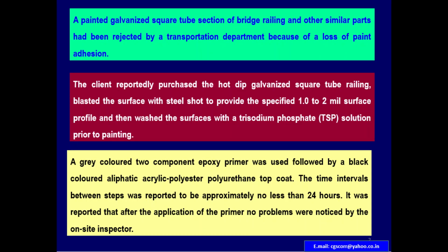A painted galvanized square tube section of bridge railing and other similar parts had been rejected by a transportation department because of a loss of paint adhesion. The client reportedly purchased the hot dip galvanized square tube railing, blasted the surface with steel shot to provide the specified 1 to 2 mil surface profile, and then washed the surfaces with a trisodium phosphate, shortly called TSP, solution prior to painting.